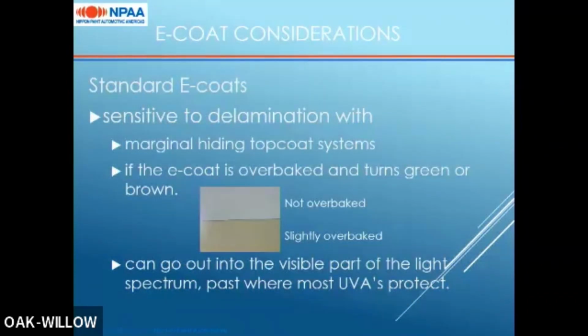But then for e-coat considerations, one of the things I've mentioned multiple times during this presentation is that most current coatings are designed to help protect the e-coat. So for this, we recommend the use of specific types. Most standard e-coats are sensitive to delamination with marginal hiding top coat systems. If the e-coat is overbaked or turns green or brown from that overbake process, it does make them more sensitive. In this example here, I just have what a typical not overbaked e-coat should look like and what a slightly overbaked e-coat should look like. Standard e-coats can also be exposed to and are sensitive to the visible portion of the light spectrum past where most UVAs would protect.